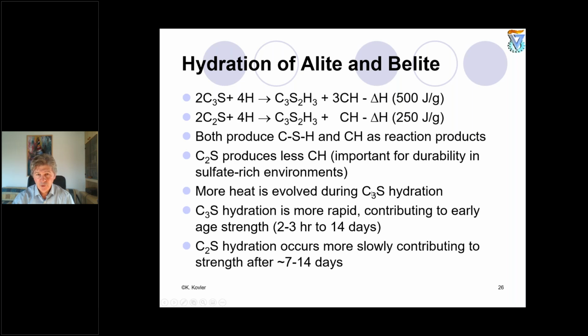More heat is evolved during alite hydration. You see the heat, 500 joules per gram. C3S hydration is more rapid, contributing to early strengths. But belite hydration occurs more slowly and contributes to the strengths after one to two weeks.